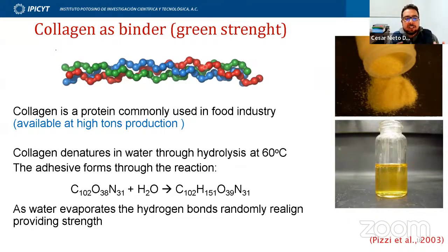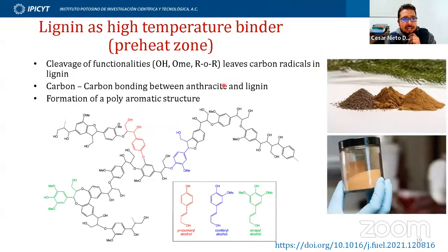We select collagen because it's a commodity that is very common in the food industry. It is made in very high tons per year. The way in which the collagen provides binding strength to the carbon fines is by a hydrolysis reaction. Water molecules, when you dissolve collagen, just interact with these carbon chains. And then when you dry the collagen, these amino acid carbon chains make hydrogen bridges between all the components of the briquettes and make it hard.